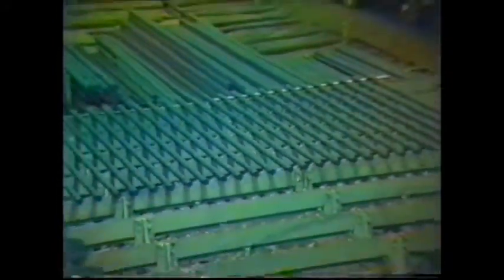The greater the reduction ratio, the original cross-section area compared to the final cross-section area, the more efficient and effective this process becomes. So, though it takes more energy to reheat and roll larger beginning ingot or strand cast sizes, these provide greater final hot reduction ratios for a given final bar size. Following hot rolling, bars will often undergo various tests for surface quality.